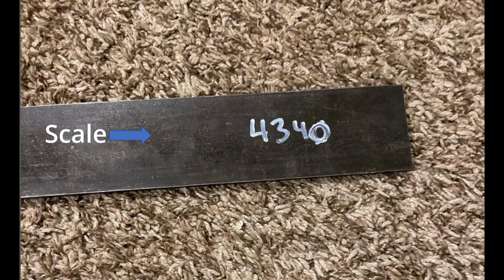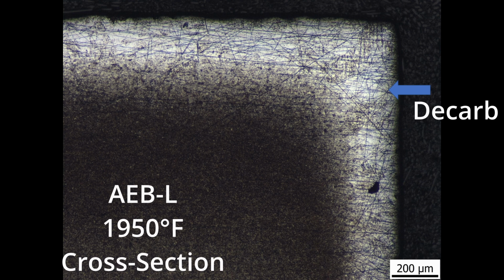One thing that datasheets often don't address is what you do to protect the steel from scale and decarburization. So scale is the black oxide that forms at the surface, but even more dangerous in some ways is the decarb layer underneath. That's a layer of steel that no longer has carbon in it and thus does not harden. So if you get a decarb layer at your edge, then the edge will not be hard, which of course is our goal. So here's a picture of some AEBL steel that was heat treated without any protection from the atmosphere, and it has a very thick decarb layer, about 0.2 millimeters thick.